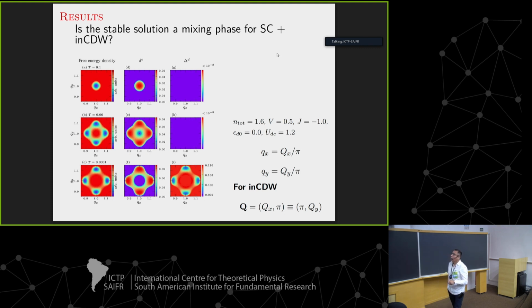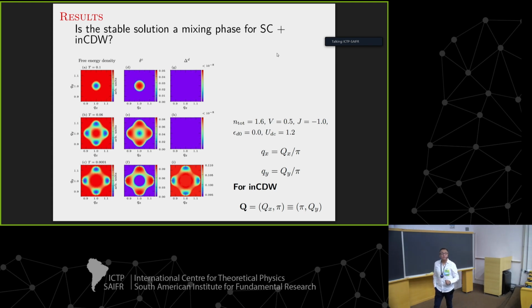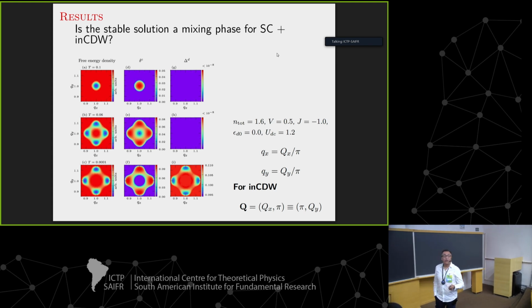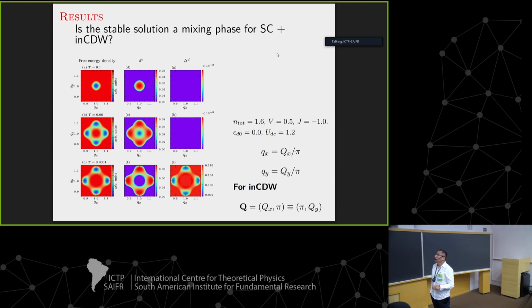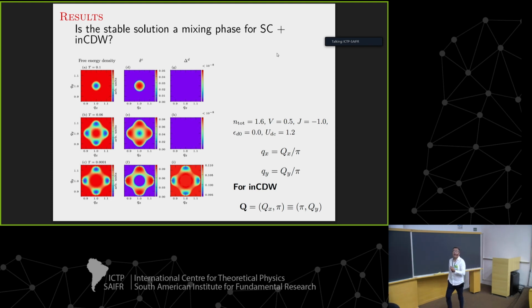If we lower the temperature even more, for instance to this value here, where it's almost 0, we still have an incommensurate charge density wave solution, but the superconducting order parameter is no longer 0. So from this panel, we can conclude that we have a coexistence between incommensurate charge density wave and superconductivity.